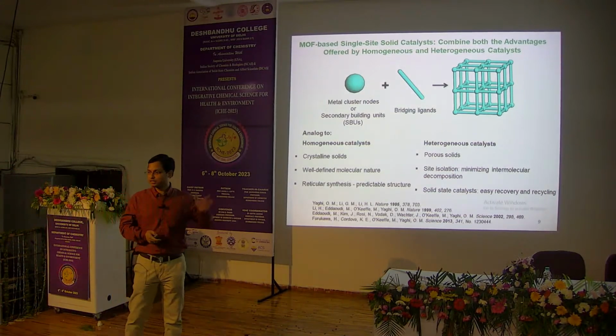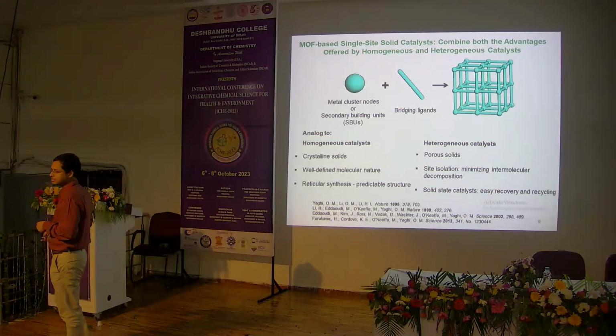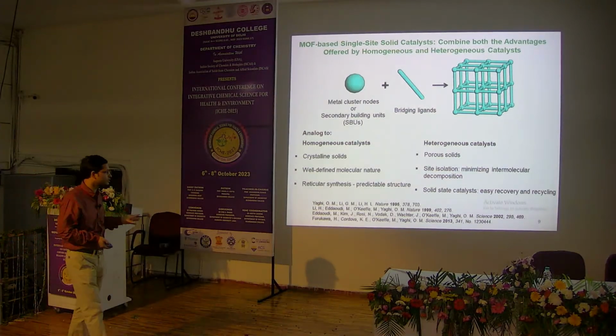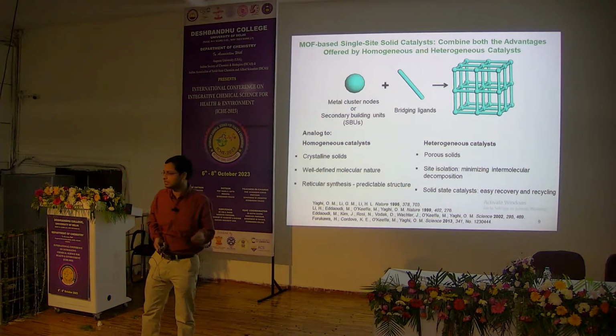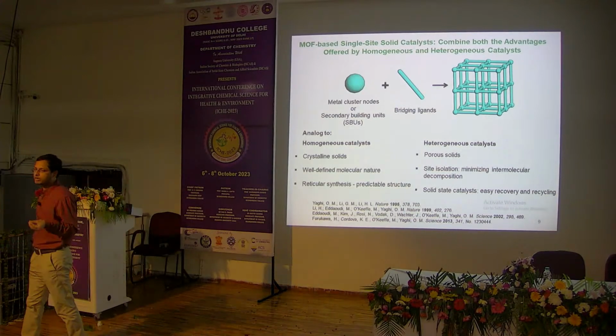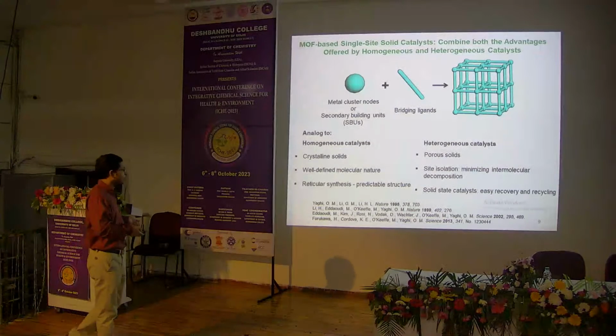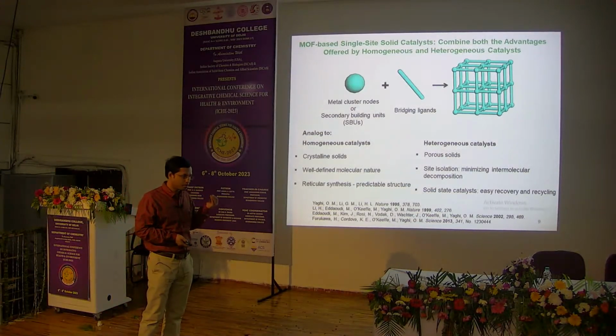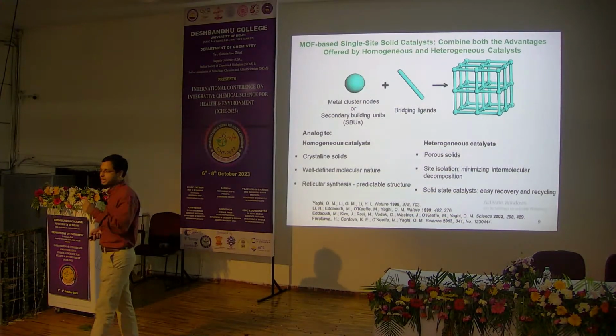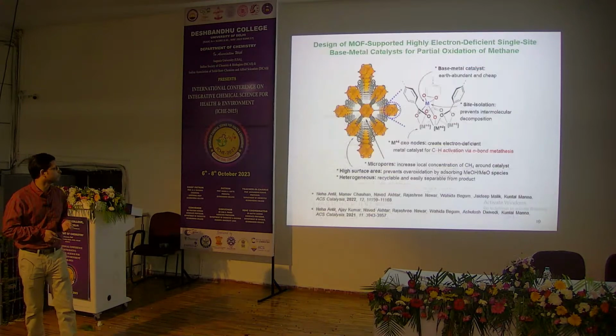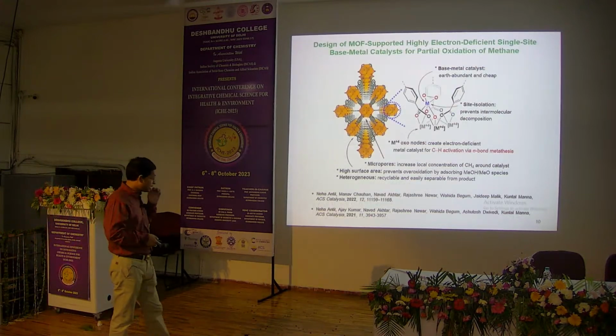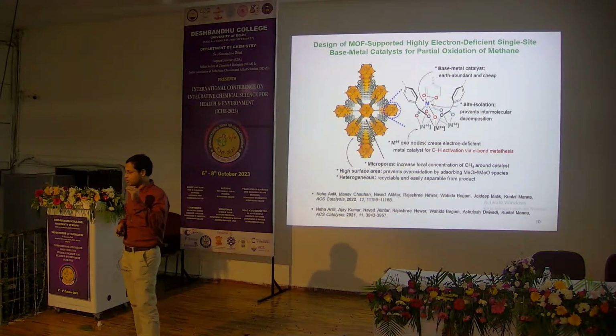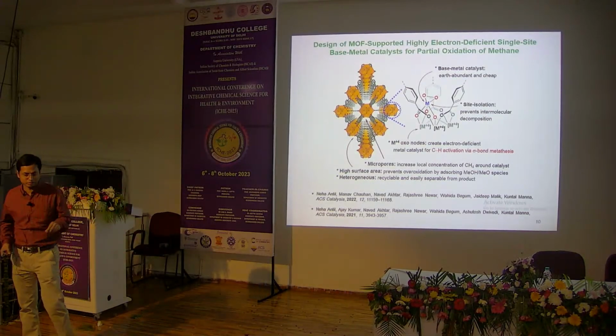Not only that, it also has the properties of heterogeneous catalysis. MOF-based catalysts are mostly heterogeneous, and we know that a heterogeneous catalyst has the advantage of recovery and recycling. And also you can make a very robust catalyst by site isolation within the MOF pores. So our idea is to activate the methane first. First is the methane activation.